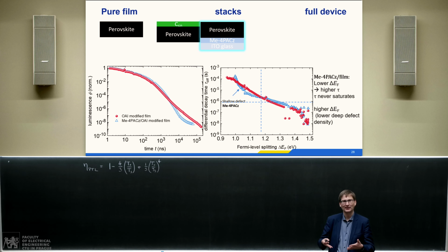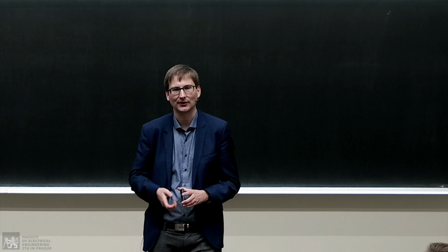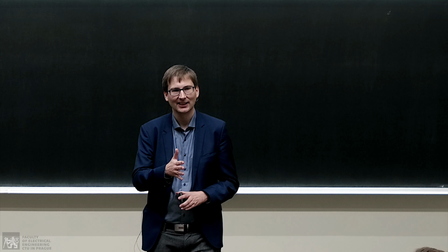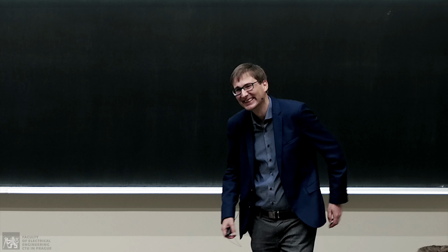I mean, I know how many photons are in one laser pulse, and if I know how many photons are in one laser pulse, I can figure out how many electron-hole pairs my laser pulse has created, because I know the absorptance of my film. I mean, this is easy to understand, right? No, but this is the generation term. And the actual concentration is after solving the equation, but I think we can discuss that later. So my question is, so this is normalized photoluminescence.